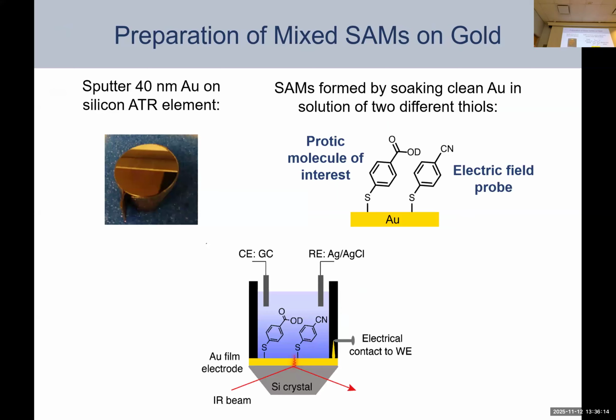So what we did, here again is a silicon ATR element coated with gold. And then on the surface, we're making a mixed self-assembled monolayer. So we're going to have some kind of protic molecule. Here we're using mercaptobenzoic acid. So the mercapto piece, sulfur, is to tether this molecule to a gold surface. And then here's the carboxylic acid portion that we're going to study protonation changes.